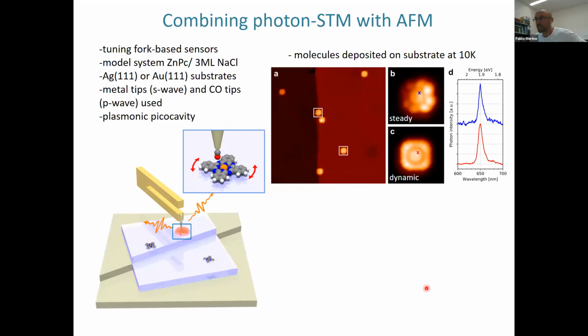So let's go to our system. What we have done is to combine a tuning fork based instrument, AFM, with optical access, and we have studied zinc phthalocyanine deposited on 3 monolayers of salt at low temperatures. And we have studied 2 different substrates, gold and silver, and with different tips, in particular metal tips with S-wave character and CO tips with P-wave character. The choice of the substrate and the choice of the tip is very important, because then you have an efficient plasmonic picocavity, which can enhance the emission from the picocavity out to the far field.